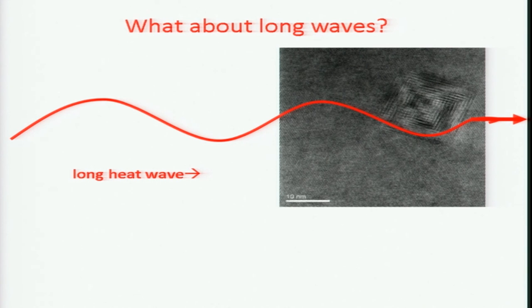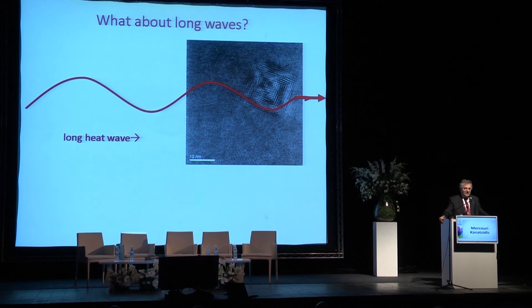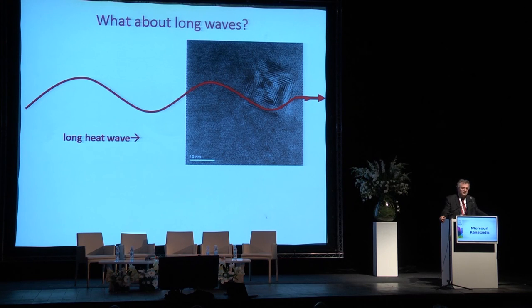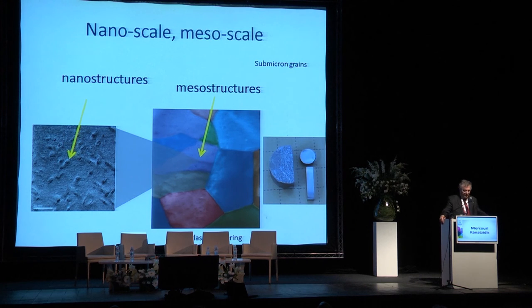And that's because the nanocrystals scatter thermal waves whose wavelength are on the order of the nanocrystal size. But what if you have a very long wave, like this? Like a tsunami, right? It's very, very long wavelength that is much longer than the size of the nanocrystal. The nanocrystal may not see that, or it may not see the nanocrystal, and it will not scatter. So we had to do something else to scatter that long wave. And so we were able to do mesostructuring.